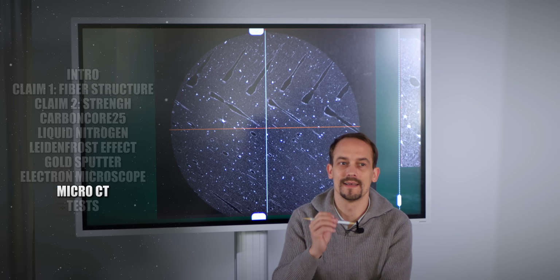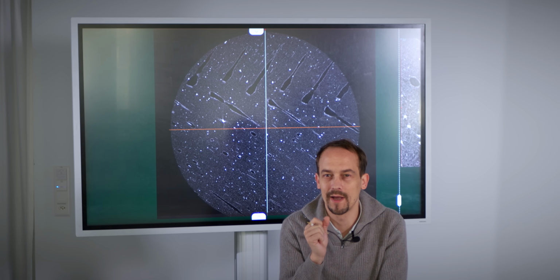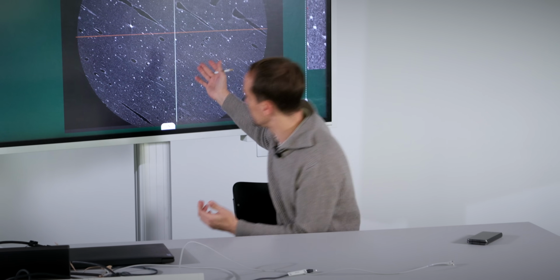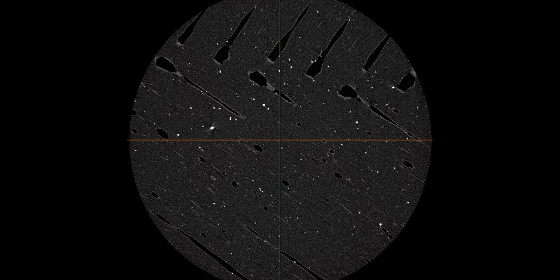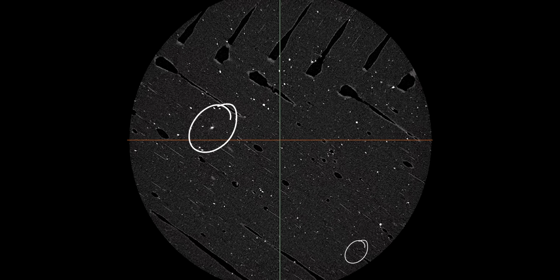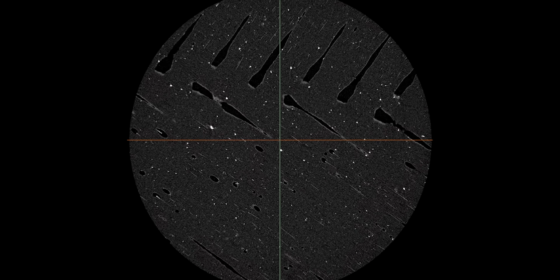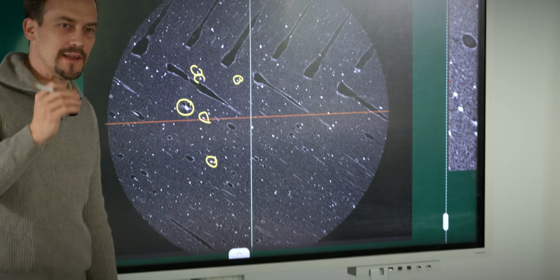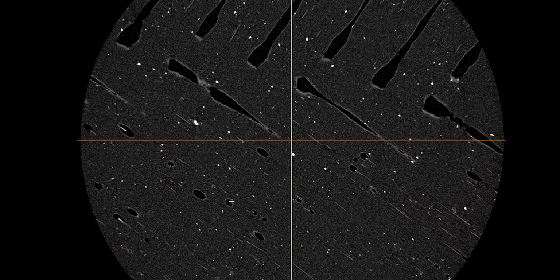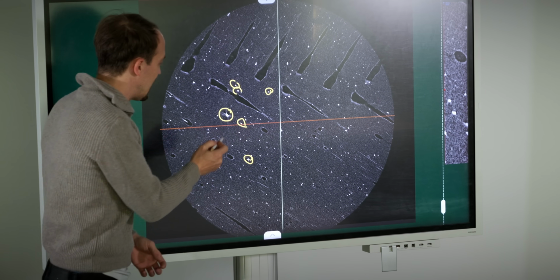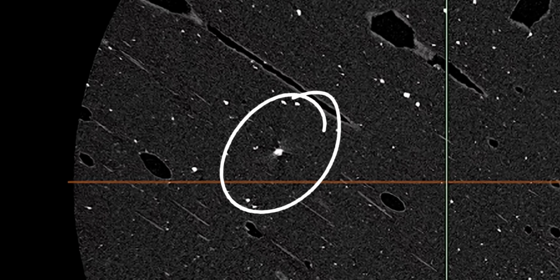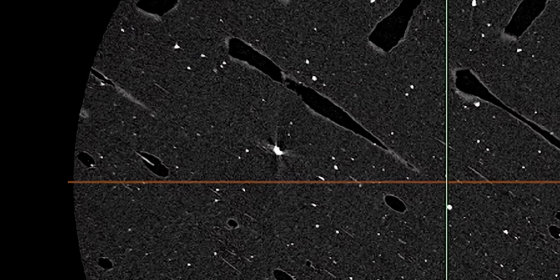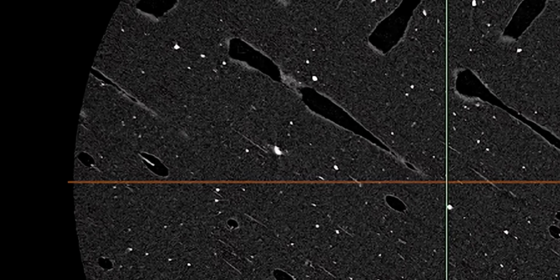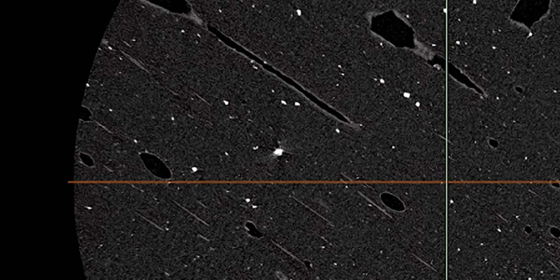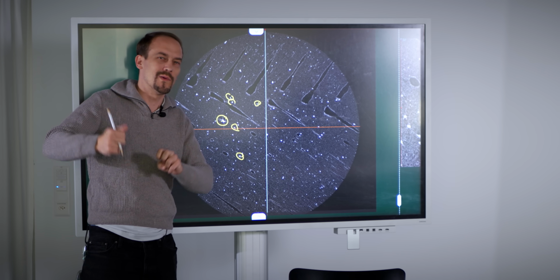The one thing that immediately jumped out at me when I opened up the CT images is the starry night that I was presented with. Here is a picture of it. We have those really bright little specks everywhere, and here is even one in a star form. They're super bright, and you have to understand, in CT imaging, brightness means density, and something like this where you can actually see those light rays emitting from it means metal content. So I was really surprised to find metal inside of a PLA-CF coextrusion filament.